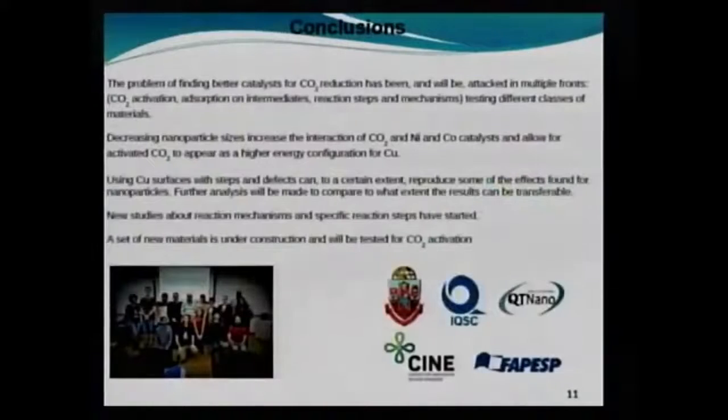So to conclude here, we are tackling this problem of CO2 reduction on 3 fronts: CO2 activation, adsorption of intermediates, and study of reaction steps. And we will test different classes of materials. We have studied the size effect and observed that decreasing the size increases the interaction of CO2 with the surfaces for nickel and cobalt and allows activated CO2 to appear for copper catalysts, for copper nanoparticles.